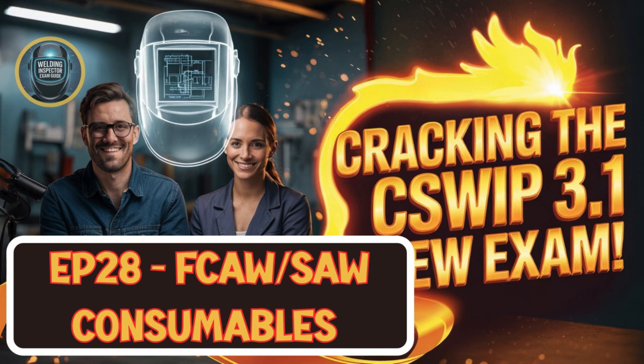Moisture pickup can lead to hydrogen getting into the weld, causing potential cracking, or gas evolution from the molten slag, which causes porosity, little bubbles trapped in the weld. Right, and porosity is a major defect. Huge defect. I've personally seen big projects face serious delays and very costly rework simply because the agglomerated flux wasn't stored properly and picked up moisture.